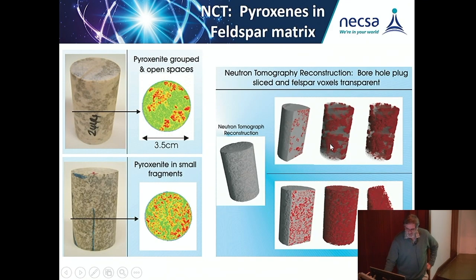Different kinds of samples with pyroxenites groups. Here we have a little bit larger one. From the outside you can actually just see those, and when you make a cross section, it's been colored red, and you can actually see how it differs from small fragments. So it's very nice to have this capability throughout the sample. But also here you can see how rugged this top part is, with a borehole plug sliced in various areas. And the feldspar is transparent, so you make it transparent, and you only see then those pyroxenites there.